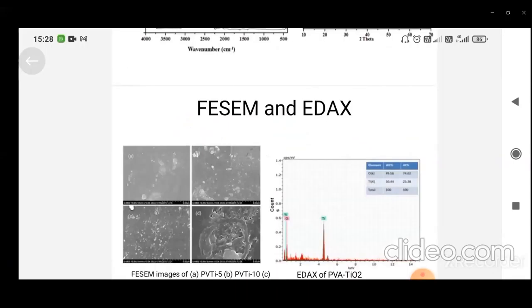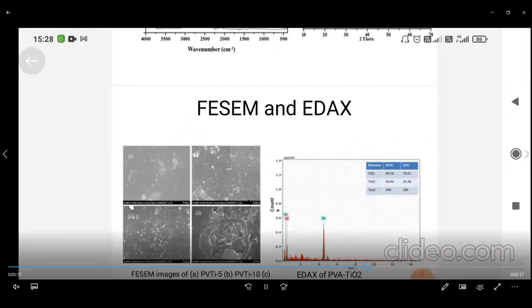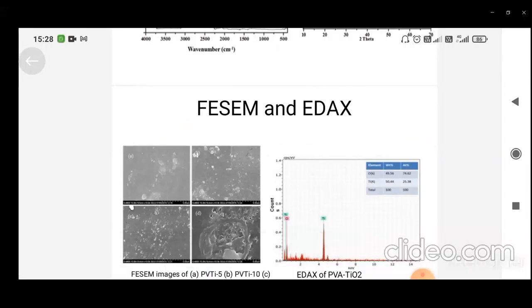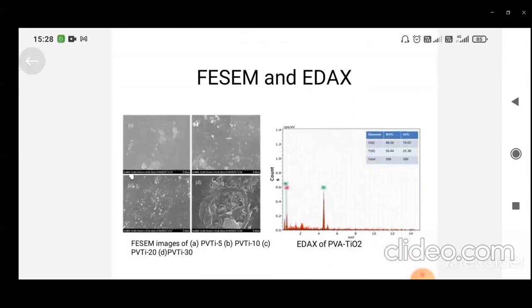The morphology is correlated to the increase in AC conductivity in polyvinyl alcohol doped with 30% of TiO2. The dielectric constant values are high at low frequency due to sufficient relaxation time for the orientation of the charged ions with the field, while they rapidly decrease at higher frequency regions with concentration of TiO2 as well as with temperature. The AC conductivity also increases with concentration of TiO2 and temperature, corresponding with dielectric losses.